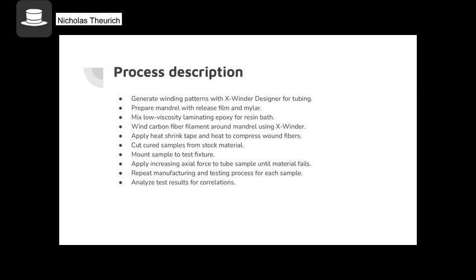Our process description is as follows. We generated the winding patterns with the X-Winder designer for the tubing. We prepared the mandrel with a mix of Mylar and also PVA release film. We would then mix the low viscosity laminating epoxy for the resin bath based on what the X-Winder would say for the actual carbon fiber required. We would then wind the carbon fiber filament around the mandrel using the X-Winder, and in this process, it is actually pre-impregnated with the epoxy bath that then runs onto the mandrel. We then would apply the heat shrink tape and heat the mandrel and heat shrink tape to compress the tape onto the mandrel, squeezing the excess epoxy out.